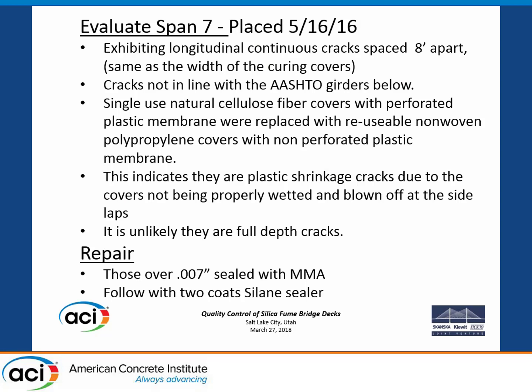So, okay, longitudinal continuous cracks 8 feet apart, cracks not in line with the AASHTO girders. Single-use fibers with perforated membrane were replaced with reusable non-woven polypropylene with non-perforated plastic membrane, different covers. Plastic shrinkage cracks due to covers not wetted and blown off. It's unlikely they're full depth. They're not curing cracks, they're plastic shrinkage cracks. Repair: MMA, 2 coats of silane.